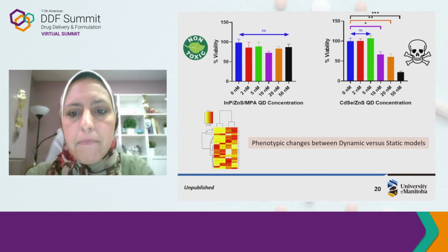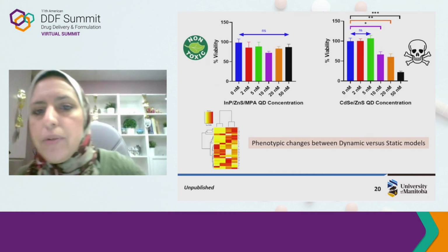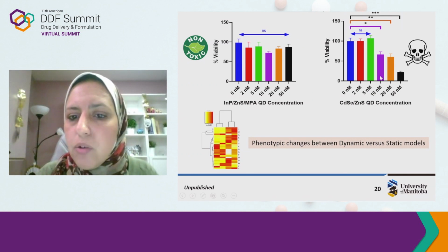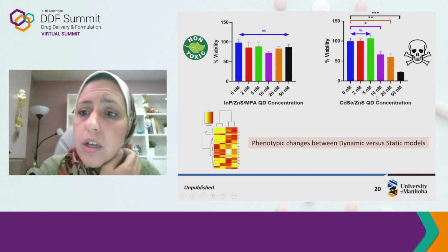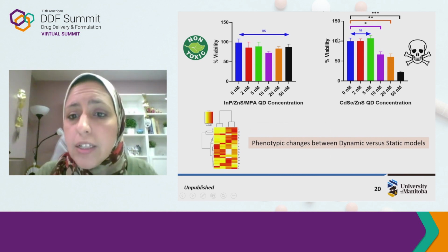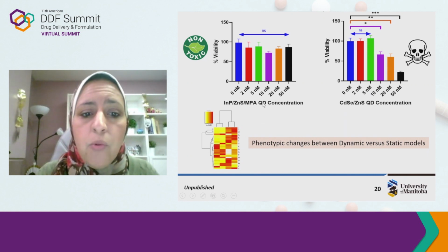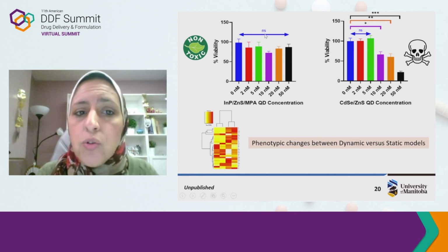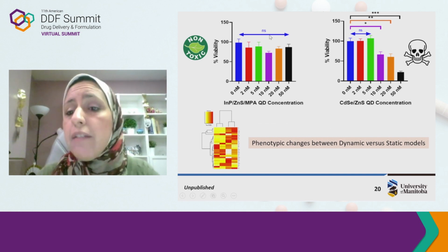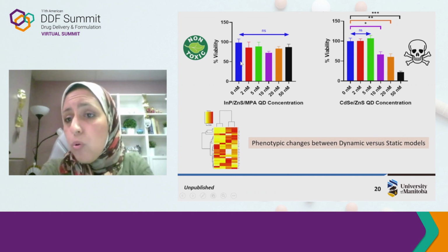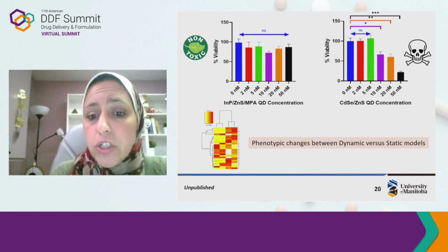And by no means, I mean, we were expecting this already, that in case of cadmium selenide quantum dots, which is the conventional type of quantum dots, they were toxic, especially going to higher concentration. But for the indium ones, they were all safe and there was no significant difference in terms of cell viability compared to the ones not exposed to nanoparticles at all.